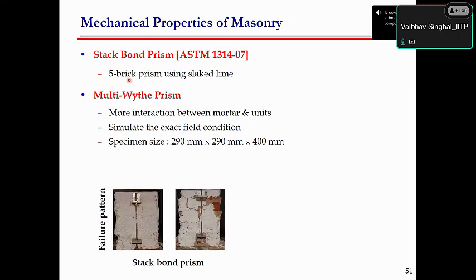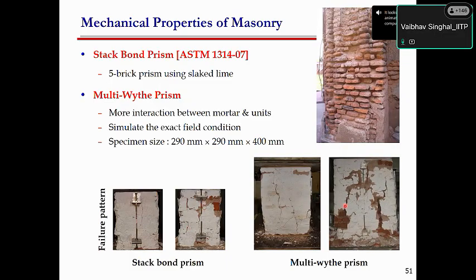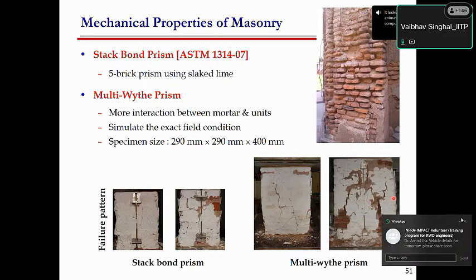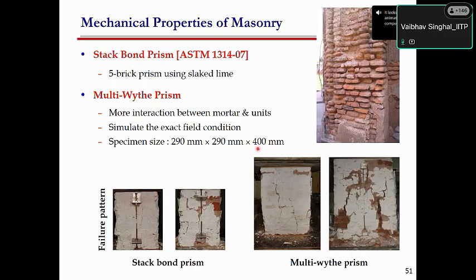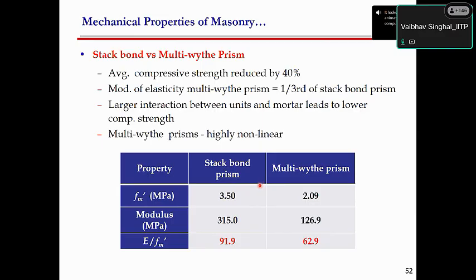So this is the first test, the 5-brick prism test. This is the small specimen of a 5-brick prism. And because these walls have multiple layers of brick, we also did a multi-wythe specimen. The specimen size is 290 by 290 by 400. And this is what the results have been found to be.